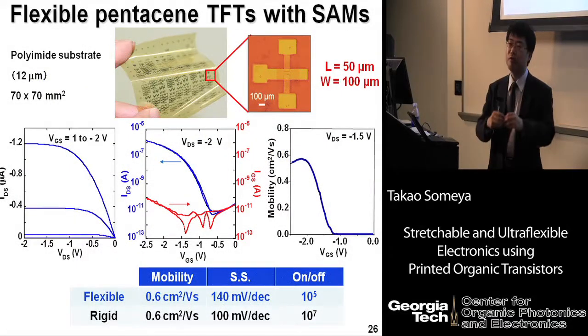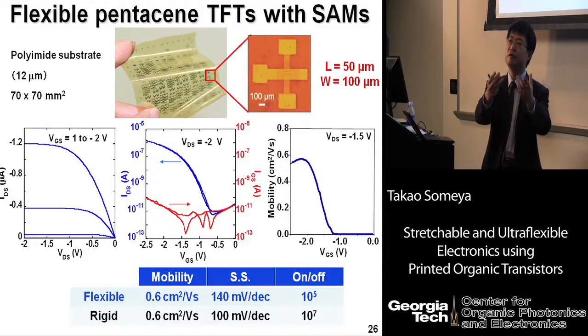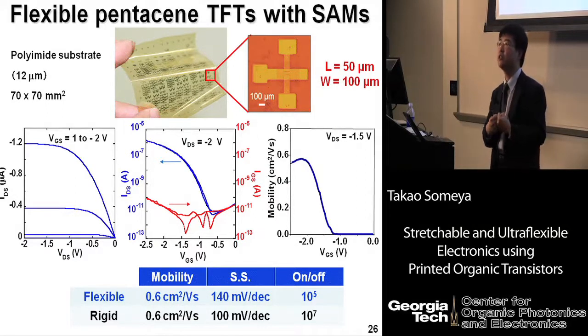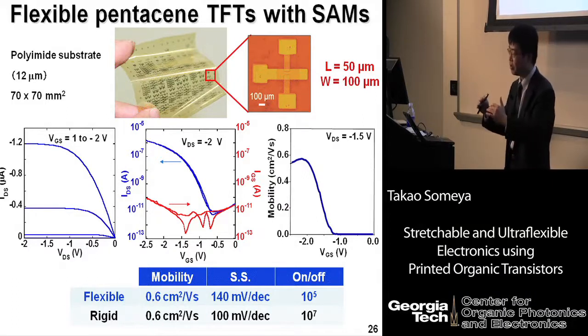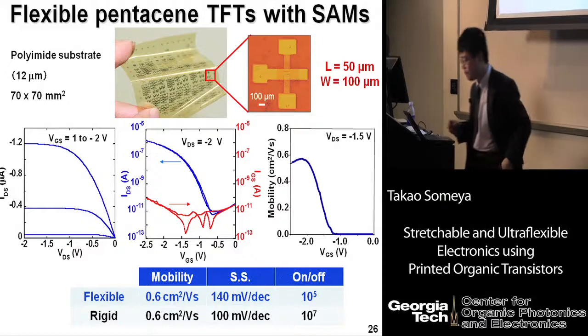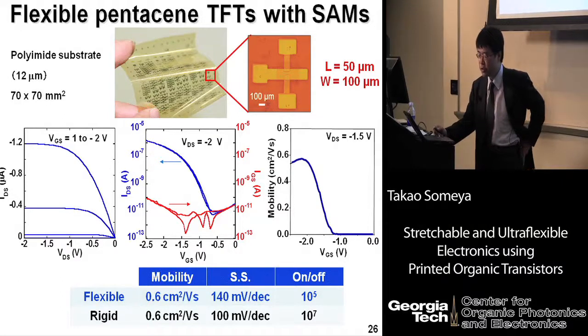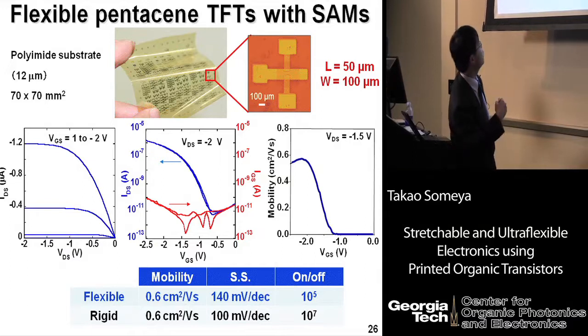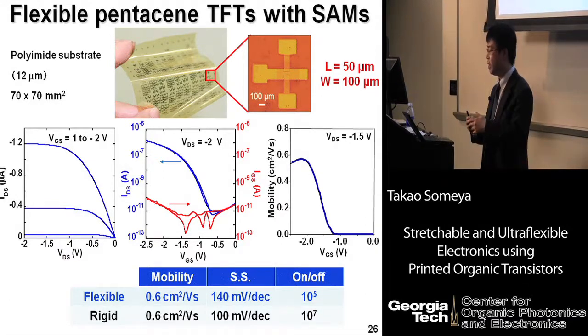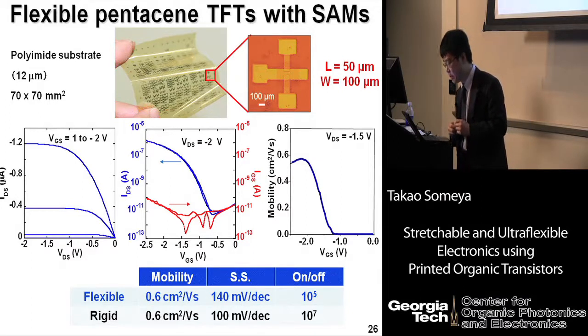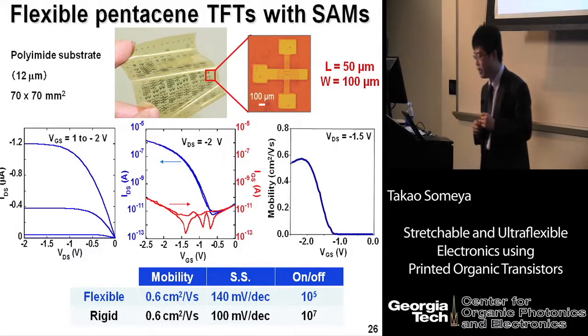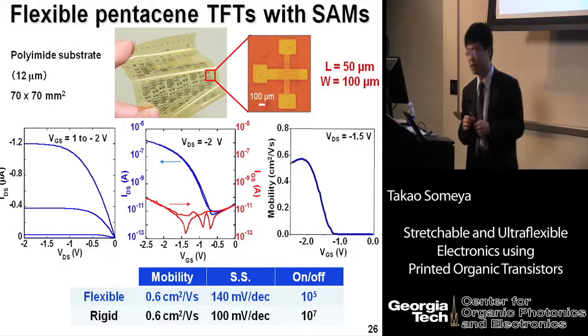In this way, we can reproduce the fabrication of high mobility organic transistors on plastic film or any other substrate. Thanks to the thin film feature of the self-assembled monolayer, the operation voltage was as low as 2 volts, yet we can achieve high mobility on plastic film. If I use pentacene, that is typically from 0.5 to 1 square centimeters per volt second. And if I use high mobility semiconductors, that can be improved significantly.